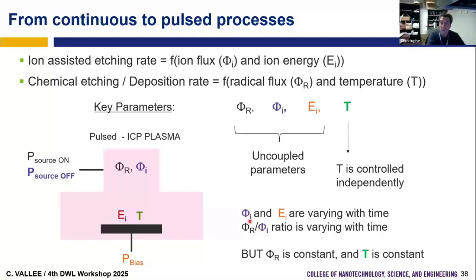Usually we modulate the ion flux. We don't modulate the radical flux. And if we modulate the ion flux, we can also modulate the ion energy by also adding a pulsing of the bias. So we can also try to modulate the ion energy. And so at the end, by pulsing, we can modulate ion flux, ion energy, and the ratio between radical flux and ion flux with time. This is very good for high aspect ratio etching and, for example, to improve aspect ratio dependent etching. It's nice to be able to modulate this ratio. But when we pulse the plasma, the radical flux usually is still constant and the temperature is still constant.